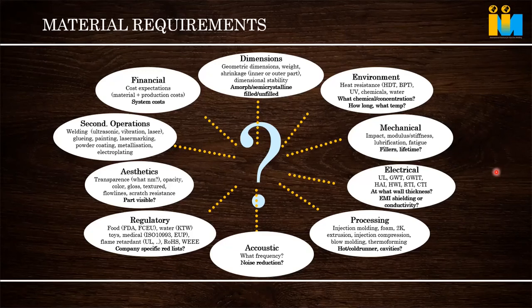But achieving dimension in POM is a little difficult because POM is a highly crystalline material compared to nylon. To make it so crystalline, only then will dimensional stability be there. POM shrinkage itself is a very, very big mystery: 2%, 3%, 2.5%, it varies a lot. So you're talking about natural nylon, right? It is not about glass-filled nylon. Natural only. If we add glass, there will be a reduction.